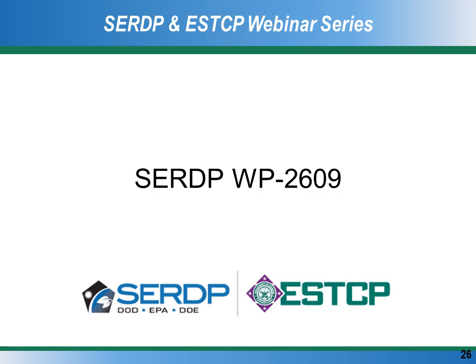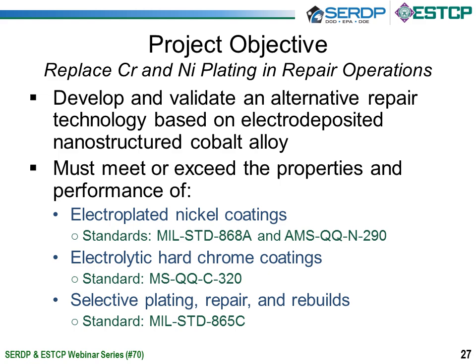So on that note, now I'll move on to our current SERDP project, which is SERDP WP 2609. The objective is to look at it less as a replacement for hard chrome, or including nickel plating in that, and specifically targeting repair operations. We're looking to develop and validate an alternative repair technology based on the nanocrystalline cobalt phosphorus alloy, as well as address some of the usability issues that have been identified in the past. Specifically, we're trying to meet and exceed the properties of both nickel coatings and electrolytic hard coatings according to the various MIL standards, and demonstrate that it can be used for selective plating and repair operations in order to rebuild worn parts.